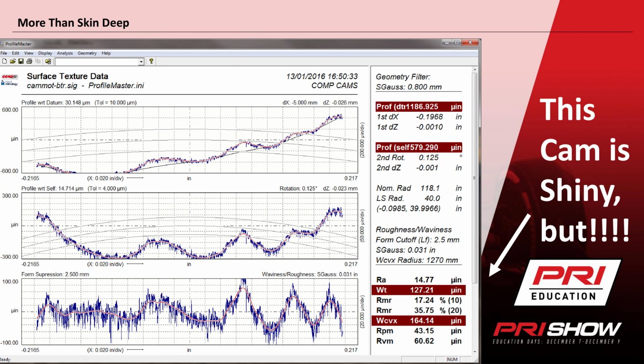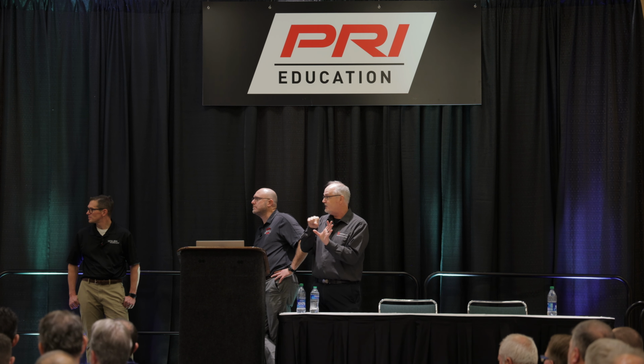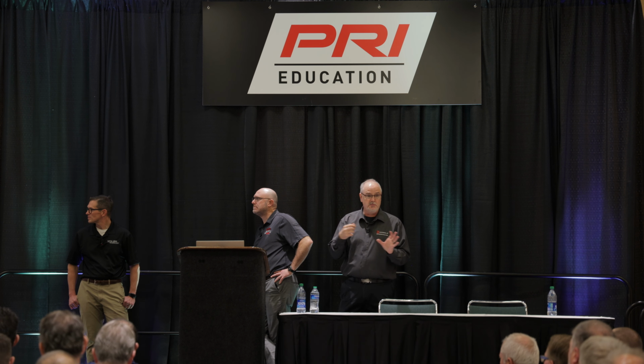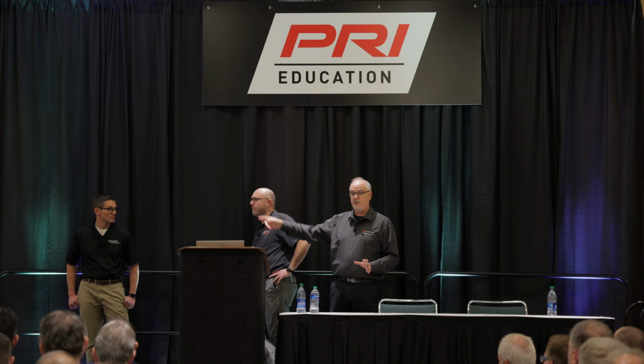It was about a 14 RA, so not a great finish, but, you know, the waviness on it is 127 microinches. So top to bottom, you look at this graph, that's the average wave. You can see from peak to peak, it's going down almost 0.3 of a thousandth smaller in the middle than the outside. Now it's hell to measure that with a micrometer, but it's really easy to do on a profilometer. So just because you polish something, you might not be doing it right.